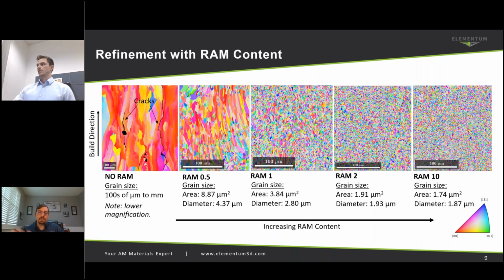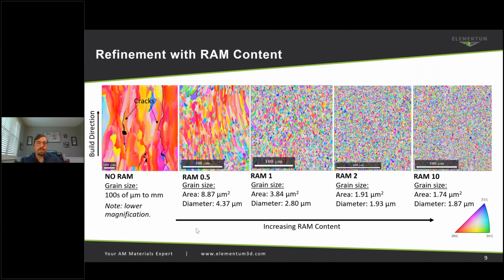But you can kind of see the progression of as we add more ceramic, the grain size of that material decreases. And so I think that's an important, at least discussion point here, is the refinement of those grains. We might see really small cracks with no material at all in some of these very hard to print nickel superalloys. But as we add our reaction synthesis products, we're seeing much smaller, much more randomly oriented grains. You see these very vertical grains where the cracks can form in between them to much smaller grains.